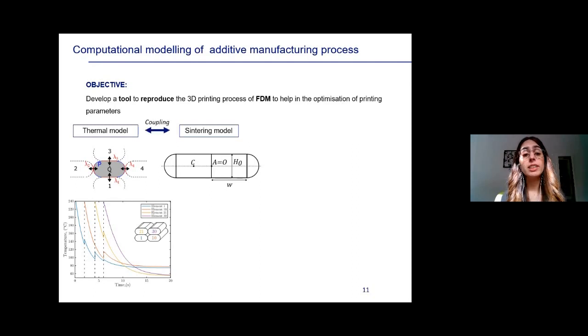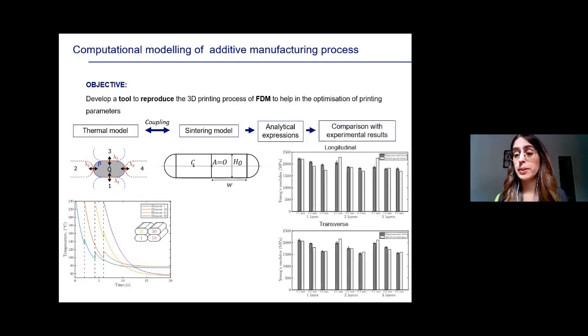We combined these 2 models with full coupling, in the sense that the temperature that the thermal model gives us allows us to update the value of the viscosity and the surface tension for the sintering model, and at the same time, the bonding between filaments has an influence on the thermal evolution. Once we have these 2 models coupled, we propose some analytical expressions to predict the void density and also the mechanical properties. With all these tools, we combine them to predict the mechanical properties, and we compare those predictions with the experimental data that we got in the first part.